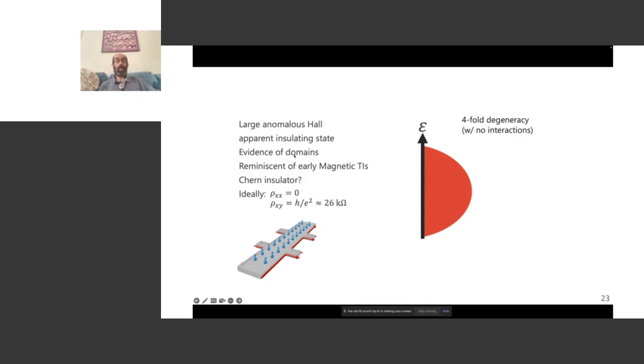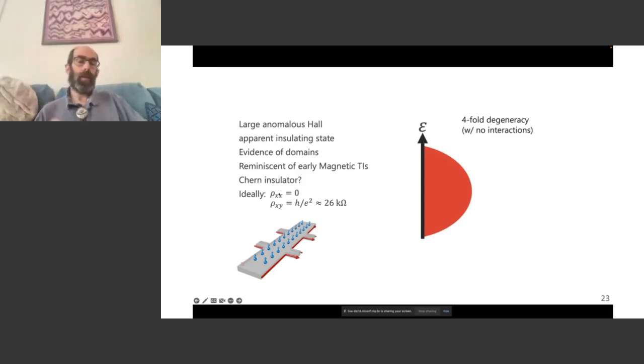We see domains that are magnetized in different directions. This looks a lot like early work on topological insulators that were magnetized. And those are analogs to the quantum Hall effect. And so it made us think maybe this is what's called a Chern insulator, an analog of the quantum Hall effect at zero magnetic field, where the resistivity and, for those of you who know, also the conductivity go to zero. But the off-diagonal terms are this quantum of resistance or quantum of conductance.